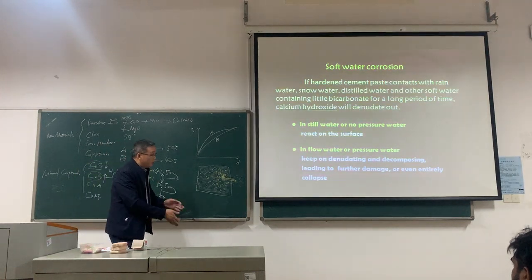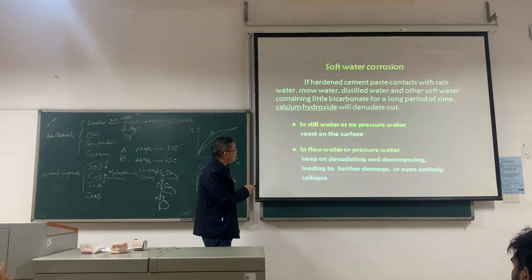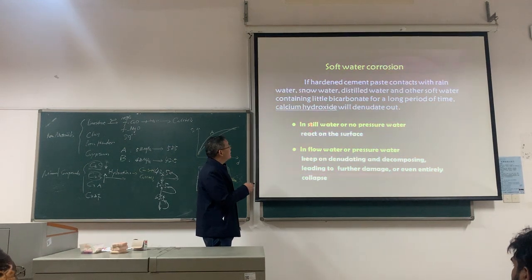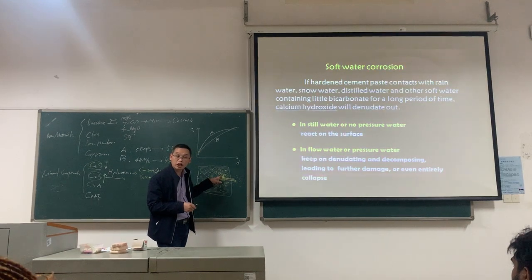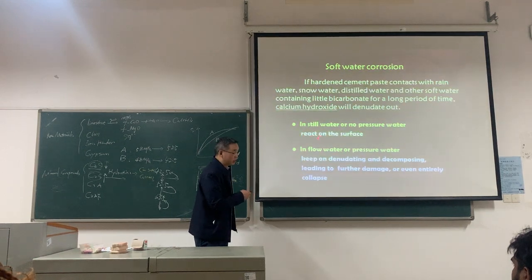So there are two conditions we need to distinguish. If in still water or no-pressure water, what kind of reaction is it? The reaction is the dissolving of the calcium hydroxide, and it just happens on the surface.